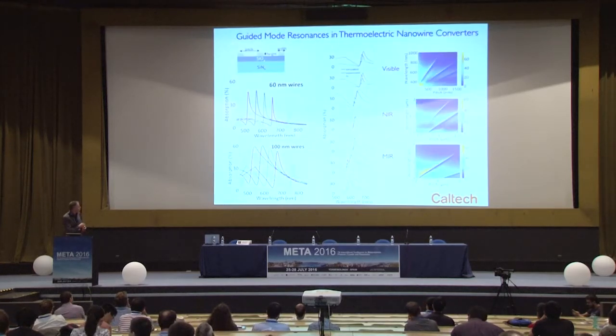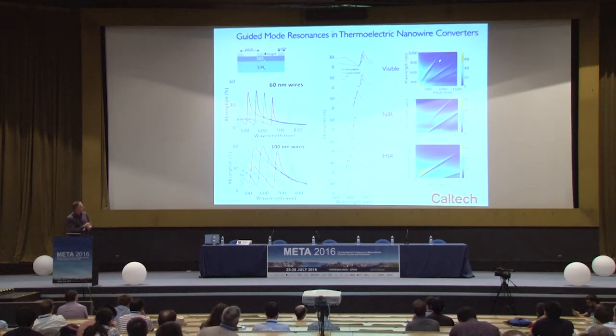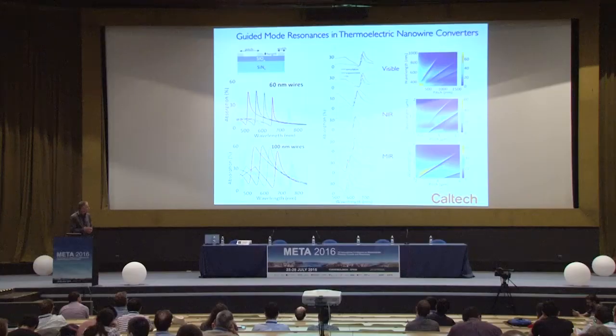And so by changing the properties of the periodicity and the line width, it's possible to have a lot of flexibility in tuning the properties of these guided mode resonance structures. Here are some experimental guided mode resonance structures. By changing the wire periodicity, it's possible to access wavelengths for guided mode resonances that extend from the visible into the mid-IR. So this actually implies the possibility of building, in a single integrated unit, a hyperspectral detector, this same material, that would be sensitive all the way from visible to mid-infrared.